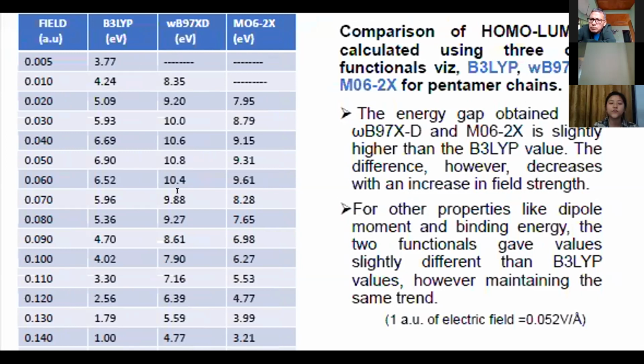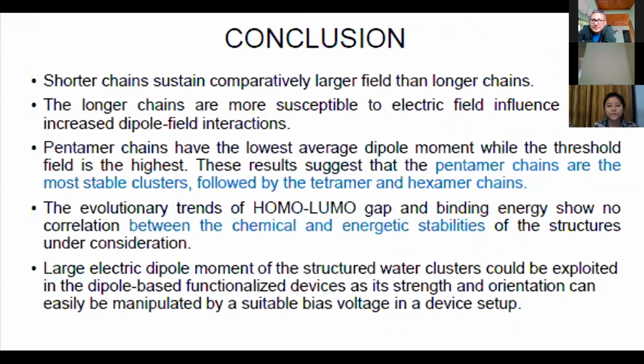decreases. Here the chain remains the same, although the field value increases. Although the values increase, we see that the chain remains the same, and the same goes for dipole moment and other properties. So from our findings, we conclude that shorter water chains are robust to a wide range of electric field, whereas the longer chains are susceptible to electric field influence, and at higher fields, the system